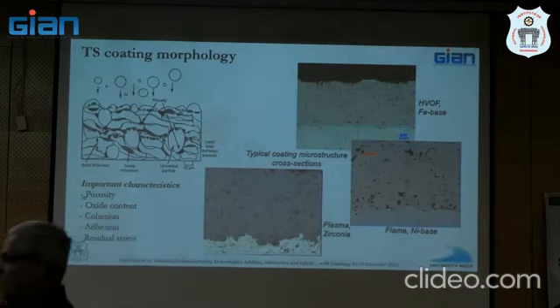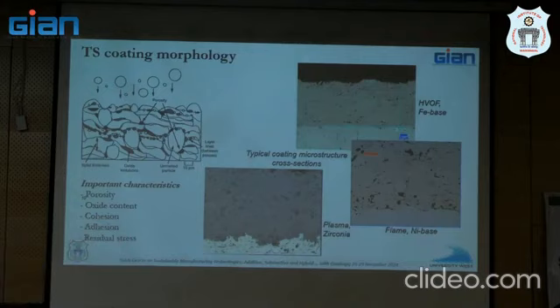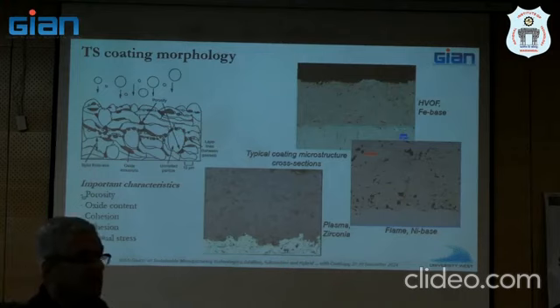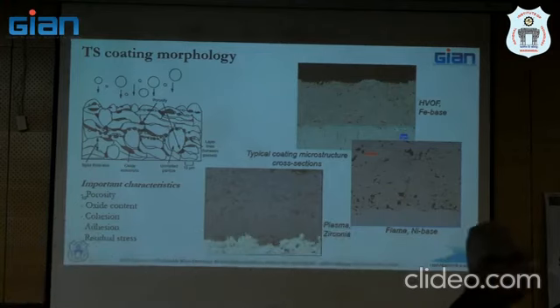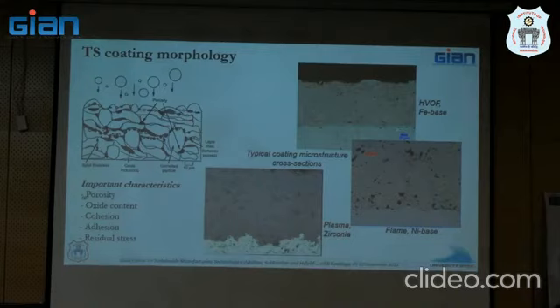Imagine that you are a coating in an aircraft, and the aircraft is taking off and landing. So what does it do? It's basically heating up and cooling, and that induces thermal stresses. How will the coating accommodate stresses if there is no porosity, right? Then it will immediately fail because of the stresses. So we asked yesterday if porosity is good or bad, and we decided it depends. So it depends. In some cases, this is all right. In other cases, if I'm looking at a wear coating, even this kind of porosity is not all right, correct?